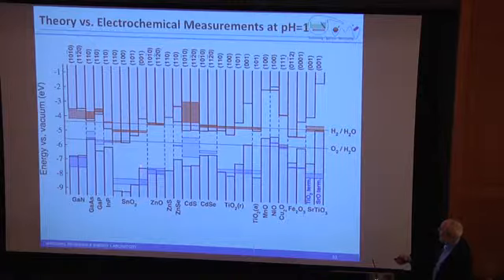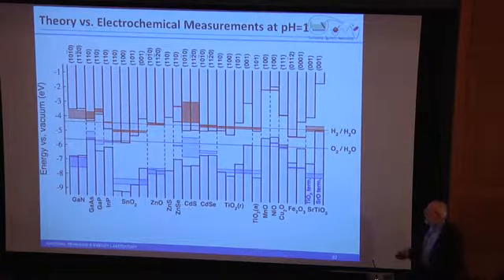This is, again, the tin oxide, where we have to be very careful which orientation we have. You can see the same thing occurs in TiO2, which of course is one of everybody's favorite water splitters, in that depending on the orientation, there's a lot of different surface energies you can have. Fortunately, most of them will split water. And then strontium titanate is right on the edge, but actually splits water, one of the best materials. But it shows that we're close. We're getting there.